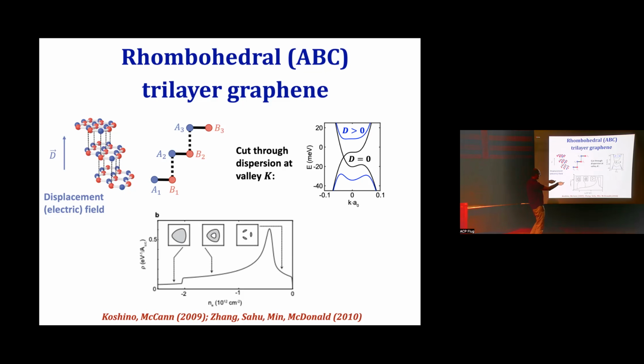But when you apply a displacement field, it actually opens a gap at small energies, and you get very flat dispersions both at the bottom of this band and the top of this band. This is what the density of states as a function of density looks like on this side of the dispersion. You see here how the Fermi surface evolves, having 3 little pockets, having an annular shape, having a connected single Fermi surface.